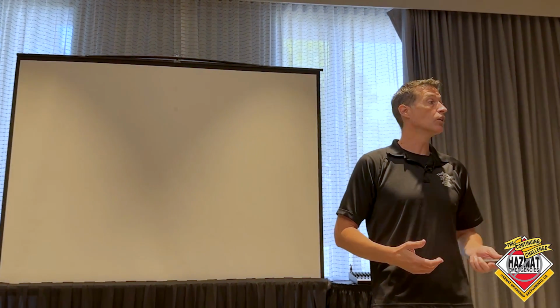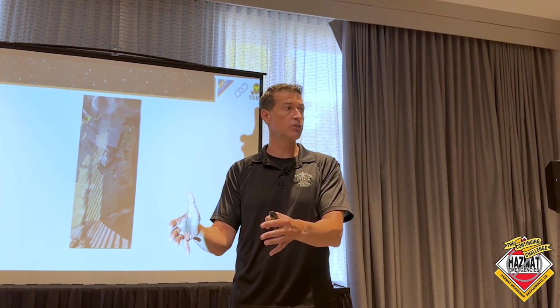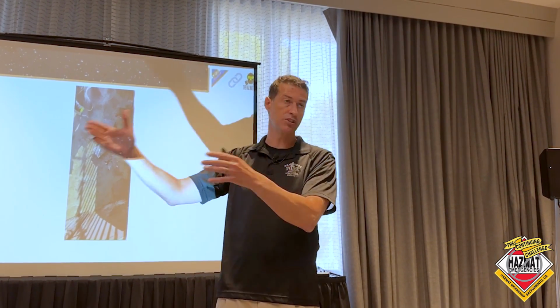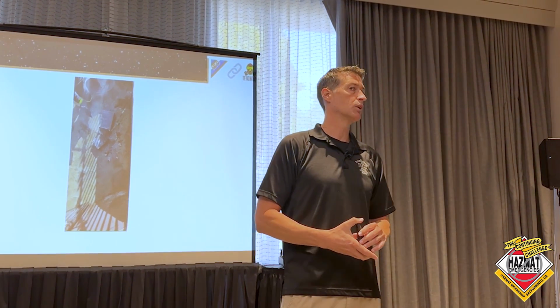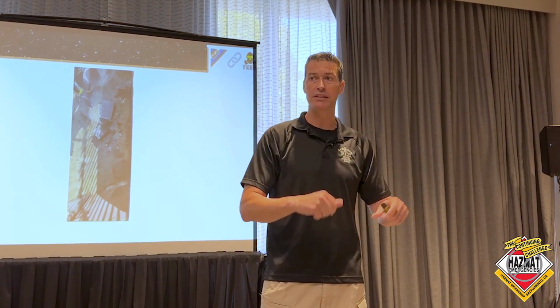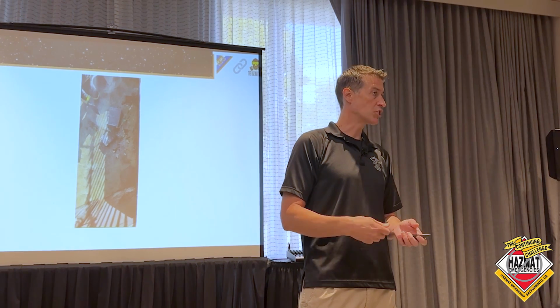What I do in San Diego is we put the batteries in a saltwater brine solution, 20% salt water. That de-energizes the batteries, and it makes the batteries essentially not capable of blowing up during the transportation to a recycling facility. So we put them in salt water, and we leave it at the residence. And we tell them, we'll come back. Don't touch it, don't mess with it. This is off-gassing hydrogen, so we leave it there with the lid slightly open for ventilation. And then our environmental health folks come back the next day and they check the bucket.